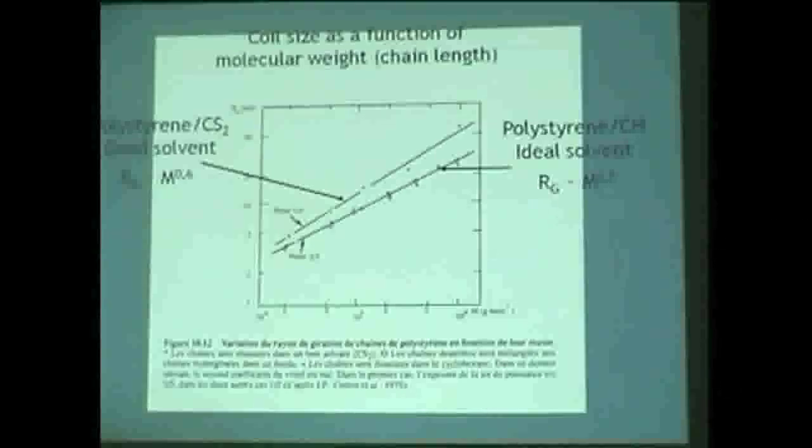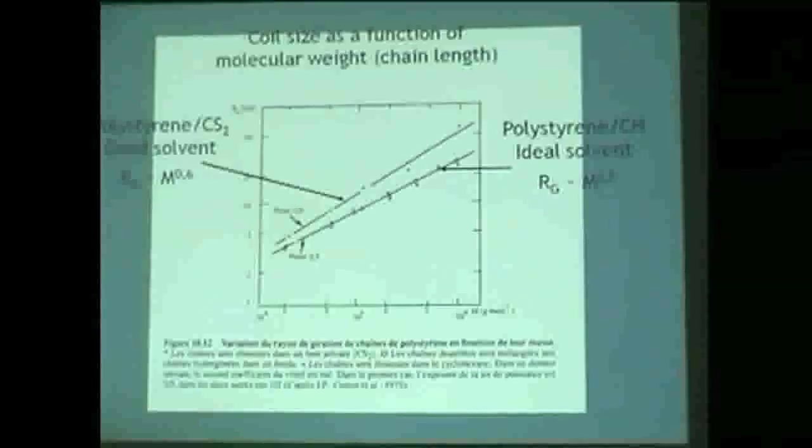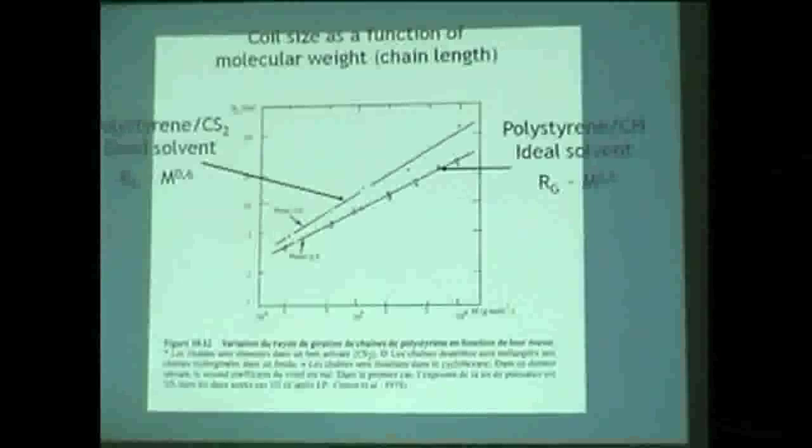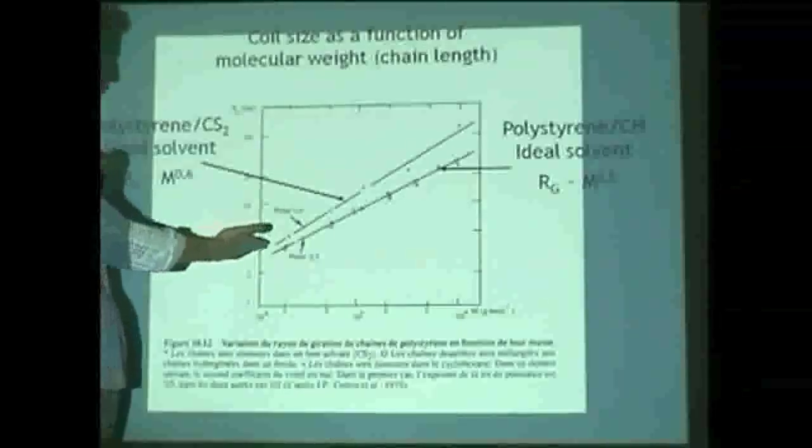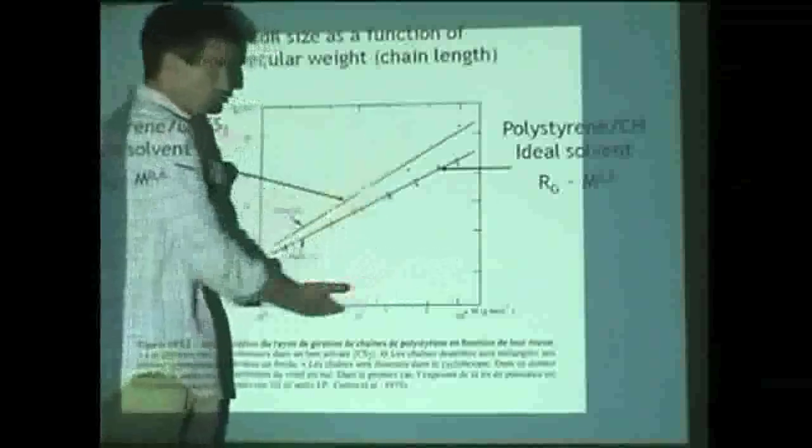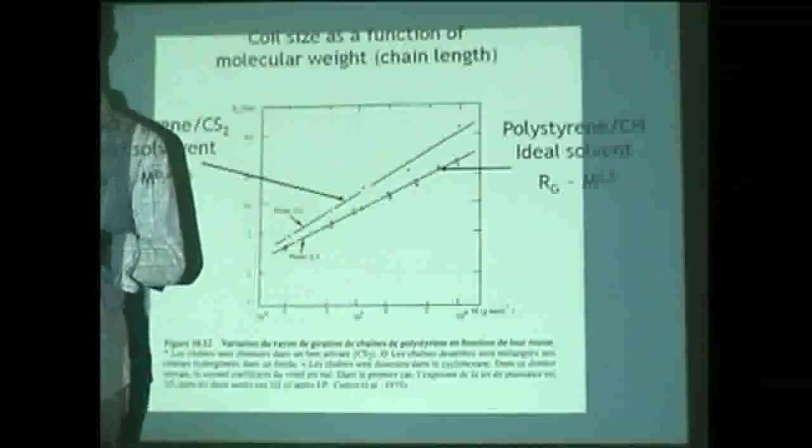and now you see it is not easy at all to measure the average value of the scalar product of the vectors. It's impossible to do, okay? Because the steps that I do, the direction in which I do the steps, are not equiprobable. Now some places are forbidden to me, okay? So this is why I will have to go further away to avoid the presence of the red lines that I've drawn on the ground. You see? So this is why I have a larger value for the gyration radius. And here also, the variation of the gyration radius with the polymer molecular weight is more rapid, is more important.